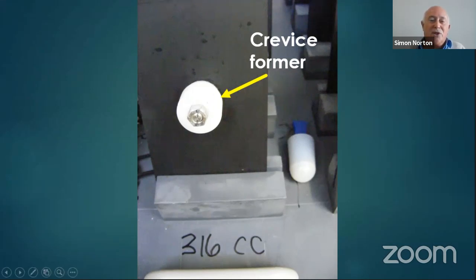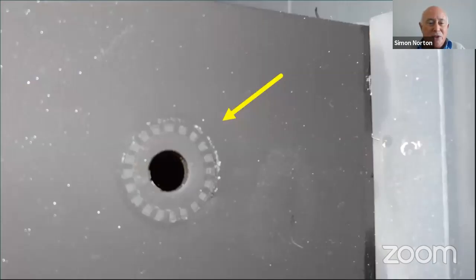And when we'd subjected it to a chamber test to simulate what would happen to it in the atmosphere, that's what it looked like under the crevice former. And if you look on the side where the arrow is, you'll see here that crevice corrosion has started to occur. So we can actually test for crevice corrosion via chamber tests in a laboratory.